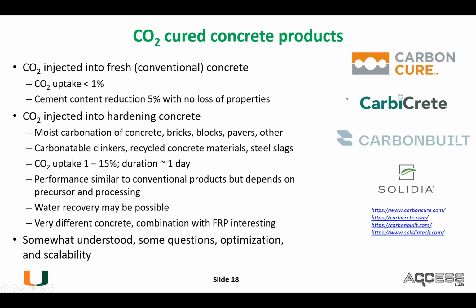The second kind of technology is, as the concrete is hardening, you inject CO2 into it. This could be concrete, bricks, blocks, pavers, or other products. In most of these cases, if you're using just standard concrete materials, again the uptake is very low, less than 1%. But if you're replacing standard concrete materials with carbonatable clinkers, for example, or steel slags or recycled concrete materials, people have actually reported higher CO2 uptakes, in some cases up to 15%.